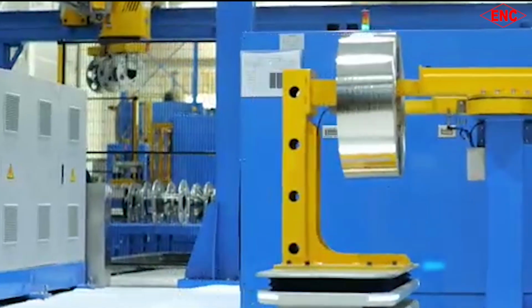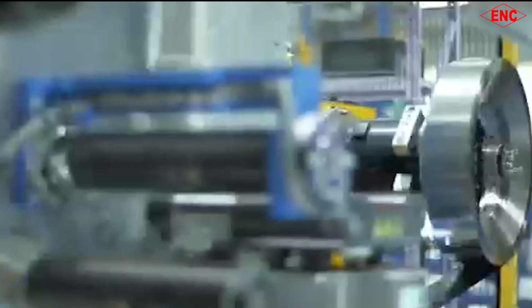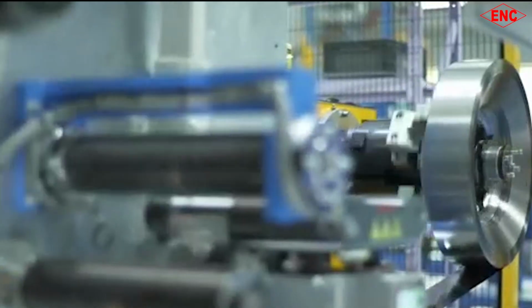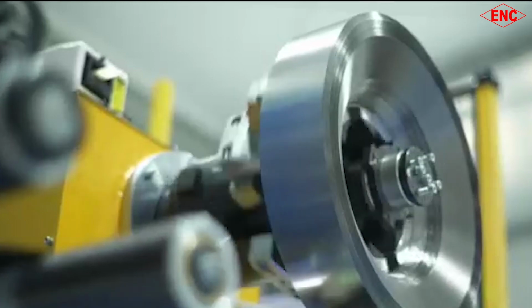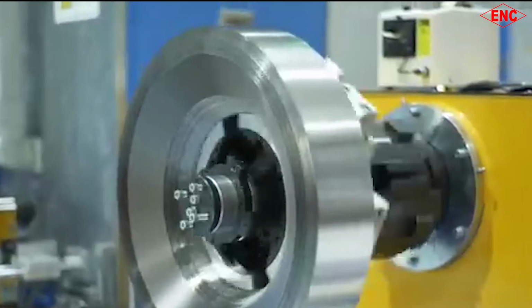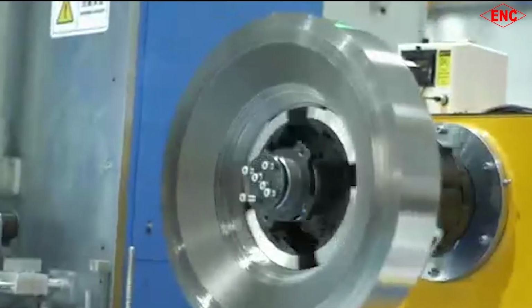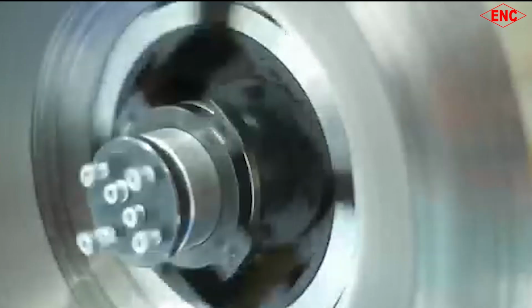In the amorphous workshop, a special AGV is used to complete the automatic feeding of the amorphous strips, and the automatic cutting machine is used for 10 to 20 stage involute cutting. Following MES instructions and drawing requirements, the automatic core winding can be realized, with automatic skew correction, online monitoring of external dimensions, winding speed up to 500 meters per minute and deviation correction accuracy of 0.2 mm.